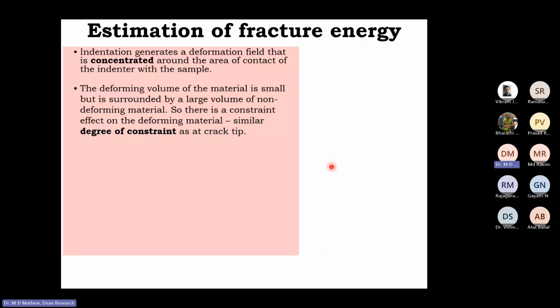Another advantage of this ball indentation test is that you can make an estimate of the fracture energy of the material without carrying out the conventional or the standard CT tests. But here again, there are a few important assumptions. First is that the indentation generates a deformation field that is concentrated around the area of contact of the indenter with the sample.